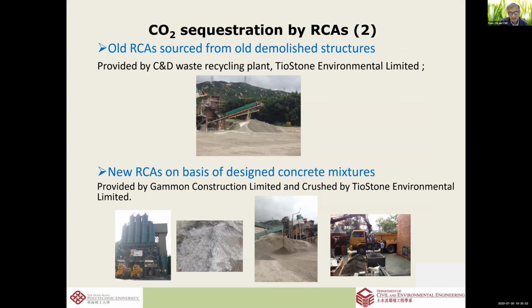After a lot of laboratory work, we produced a large batch of concrete from a batching plant, and then demolished it in a recycle plant, and then collected this recycled material to the lab. And this we call a new RCA. It is 6 months old. And then there's an old RCA, which is receiving demolished concrete from a real demolition site and then crushing it, and then we collect those to our lab.